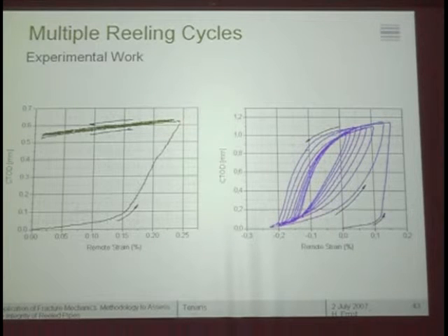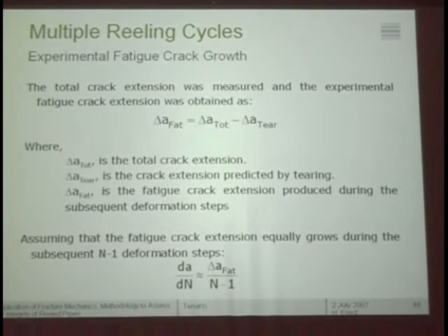We went to some value here, and we unloaded to about 0 strain, back and forth, and this is the amount of delta CTOD that we see here, very little. This is the real thing, not based on the deformation theory, where you will get something like this. If you believe the deformation theory, even if you are unloading, the delta CTOD will be all this much. And this is another example of what we did. This is a little extreme, because we went all the way in negative terms, in terms of strain, as we did in positive, which is really completely crazy, but just to see what happened.